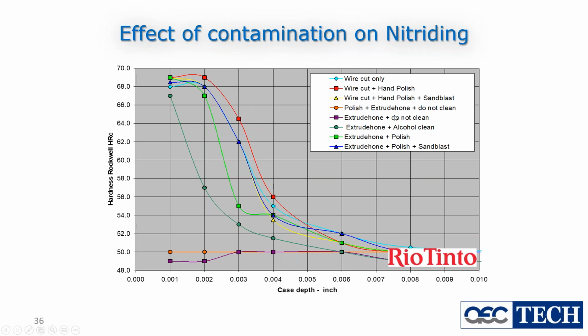This is because the extrude hone is a waxy compound, and it leaves behind a layer on the surface of the steel. And just that ever such thin layer of oiliness that comes after the extrude hone is enough to completely and utterly stop the nitriding process. Look, there is no impact at all of the nitriding process. You might as well have not even bothered putting the die in the reactor.